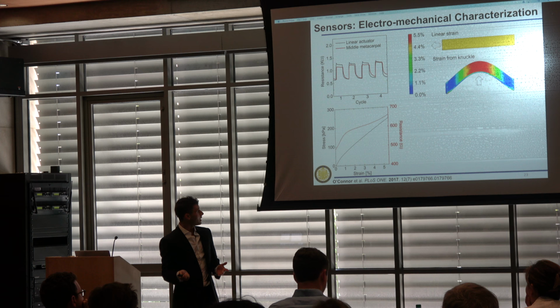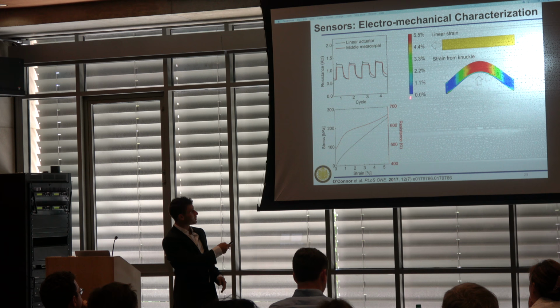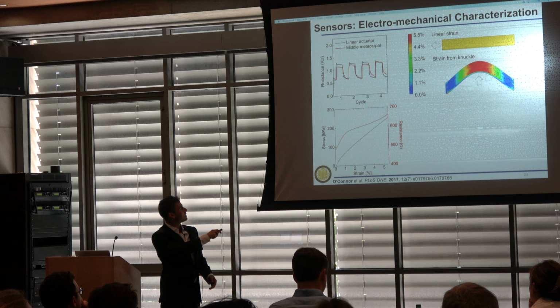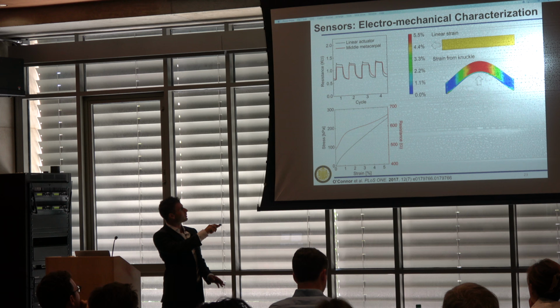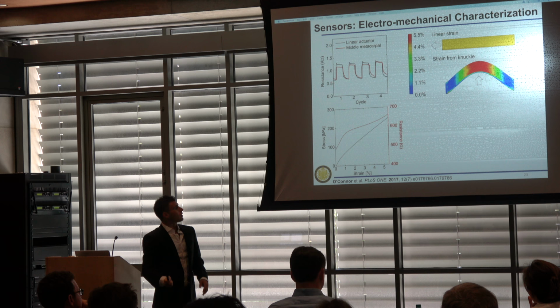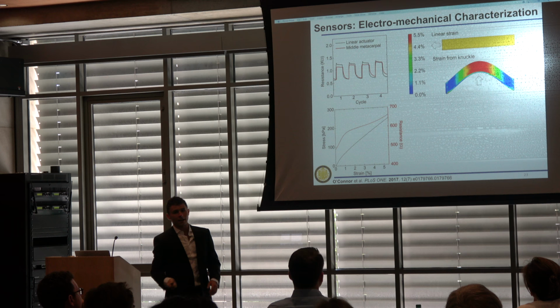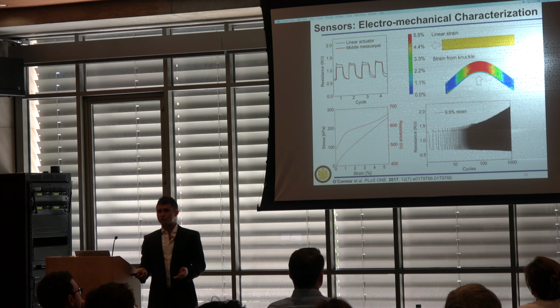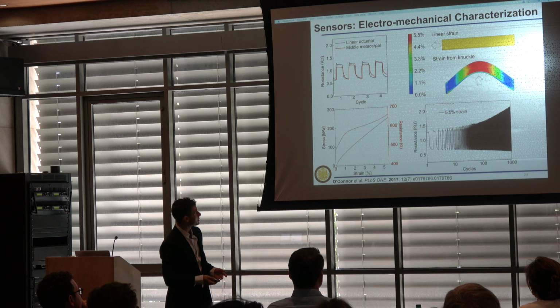Then we have to know whether the resistance change is linearly dependent on strain or nonlinear. So we do resistance versus strain, and we see this nonlinear dependence. It's a sharp increase at low strains, and at a little over 1% strain, it seems to level out. So there are almost two strain regimes here. We integrate the resistance versus strain curve with the finite element analysis model, and we get about 5.5% peak strain. We then took some of these sensors and stretched them 1,000 times at 5.5% strain to see the resilience of these sensors over many, many cycles.